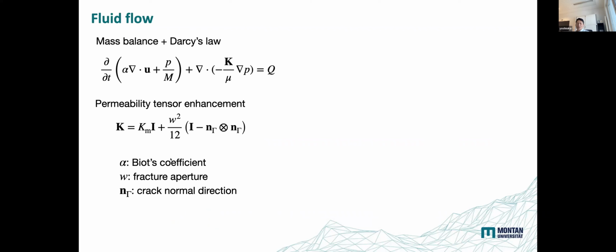And then the remaining variable we wish to find is the fluid pressure. And for fluid pressure, we use Darcy's law. So this is the permeability tensor, and the permeability tensor is enhanced using the cubic law. Well, if you watched last week's webinar, this approach may be obsolete, but I still use it. So this W is the fracture aperture, and as the fracture aperture changes, this permeability is enhanced, and also this permeability is given as a full tensor. So I also want to know the crack normal direction. Okay, so that's how we get fluid pressure.